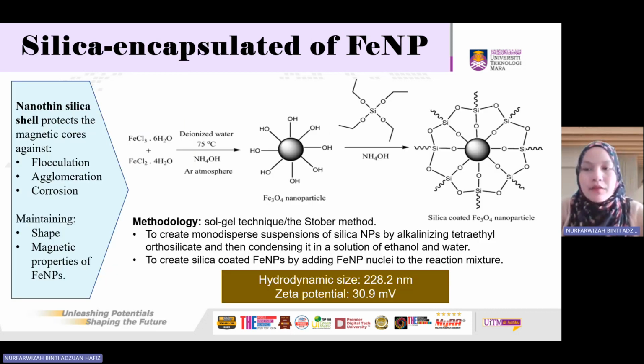Next is capping with amorphous silica. The nanothin silica shell protects the magnetic cores against flocculation, agglomeration, and corrosion while maintaining the shape and magnetic properties of iron oxide nanoparticle. In addition to enhancing the magnetic nanoparticle stability, the silica covering serves as a scaffold for the attachment of various functional groups, and silica-coated iron oxide nanoparticle can be made using the sol-gel technique.